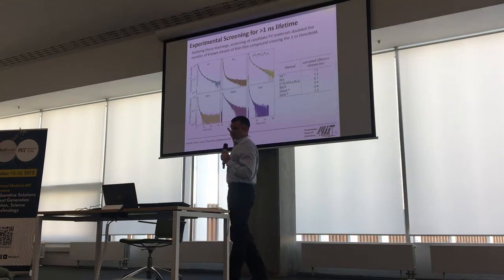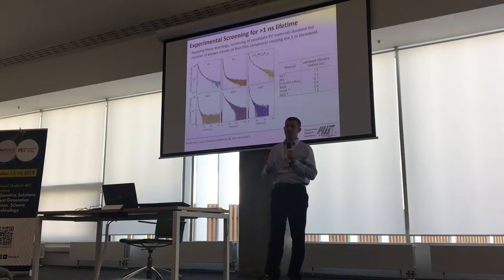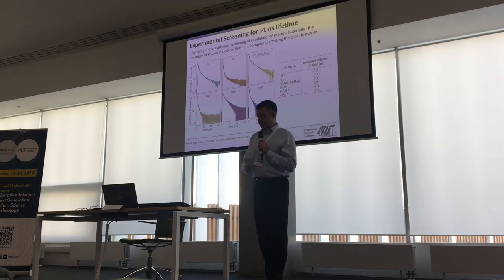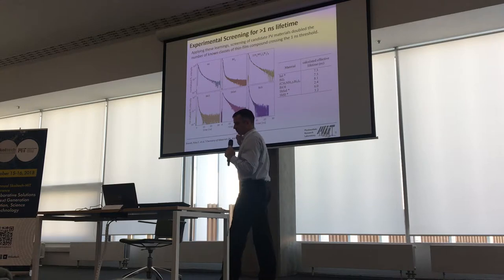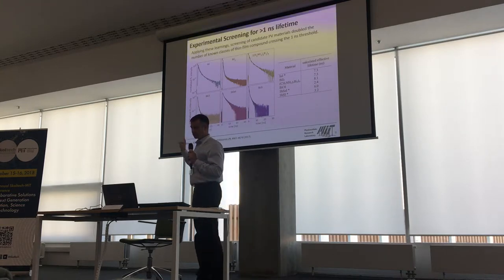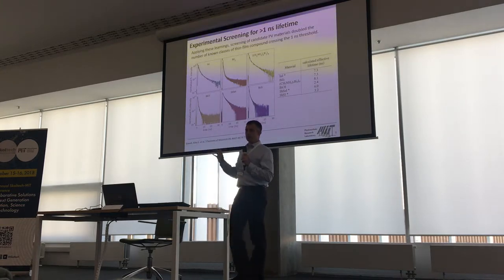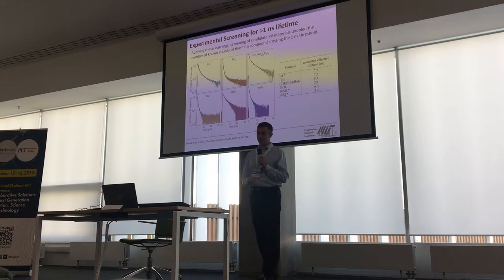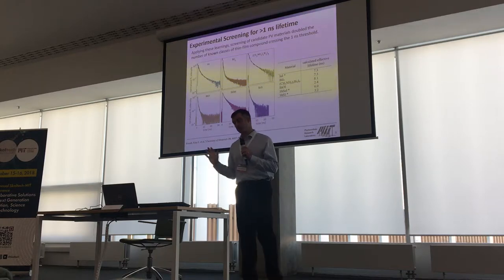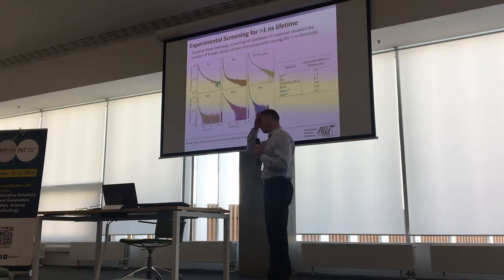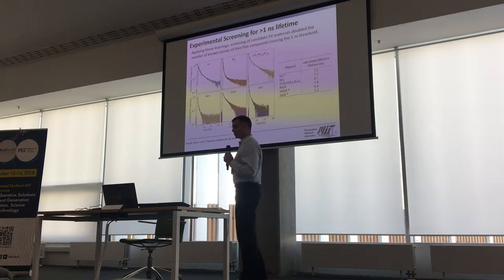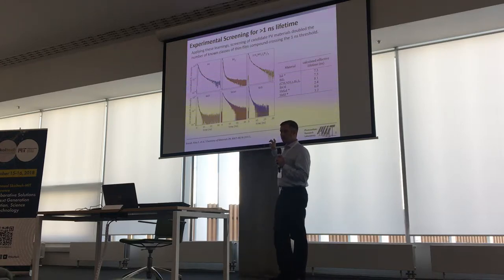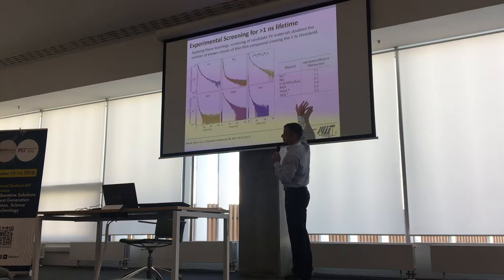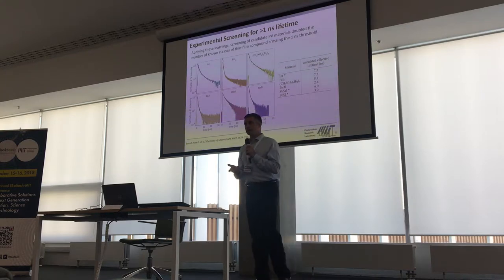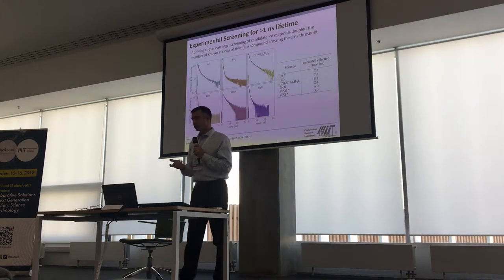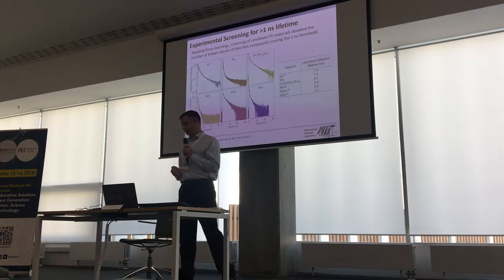And this was a very successful paper in the sense that it validated the prediction based on the high throughput screening. We synthesized 6 materials in 6 months. This was twisting arms in the laboratory. People said it couldn't be done, it was too fast, but we got 6 materials grown in 6 months, and every single one of them exhibited a minority carrier lifetime greater than 1 nanosecond, which is a measure of electronic quality that indicates promise for a solar cell or optoelectronic device application.